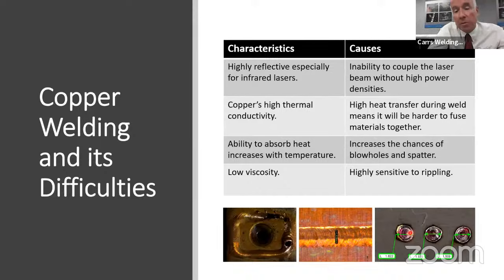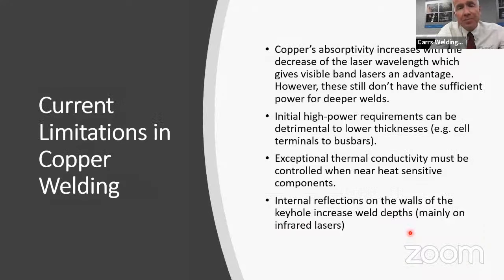Typically with the IPG and the wobble welding. I say that because we've done quite a few coupled bus bar systems in the past with pulsed YAGs, and when you're only using a very high pulsed energy for connecting copper, you do get a very variable result, and so I don't recommend that. It's possible, but it's something we steer away from now. And there's a few points there about what I would avoid when you are welding copper.